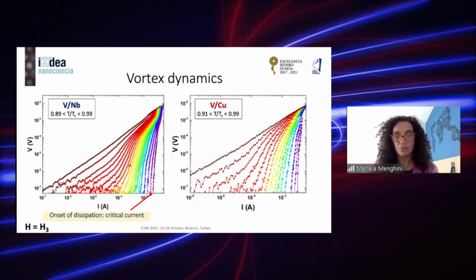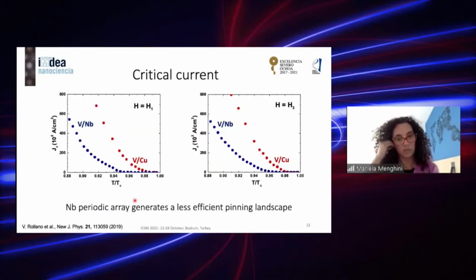Okay, so the next thing that we did was to look into the vortex dynamics in this system. Here we have, just to compare, IV curves done in this vanadium niobium hybrid structure, and also the vanadium copper hybrid structure. From here we can determine, as usual, the critical current in these two systems, and this is what is plotted here. We see that this niobium periodic array of triangles generates a much less efficient pinning potential for the vortices, so we see a decrease of the critical current compared to the case of the vanadium copper hybrid.